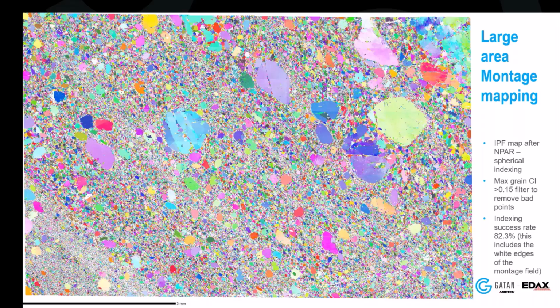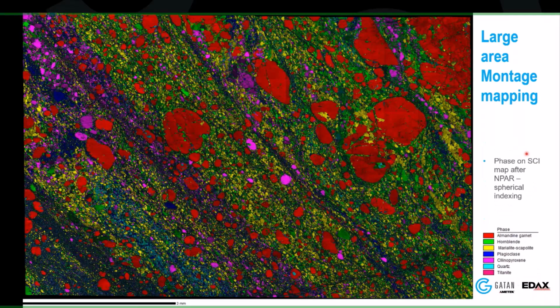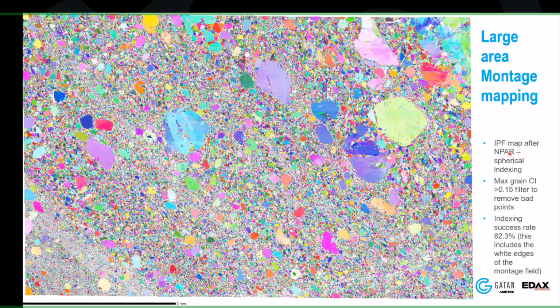And again, if you really zoomed in on here, which I can't really do live, but here's a little inclusion in this guy down here. Again, you can see very fine level deformation across a lot of this material. Again, some grain fracturing up here. And of course, this area down here as well. So again, this is where we're looking at the very large area mapping all into one shot. There are details on one of these maps about how big this was. I think it was 25 million data points. So this is roughly 25 million data points that was collected in an overnight run.